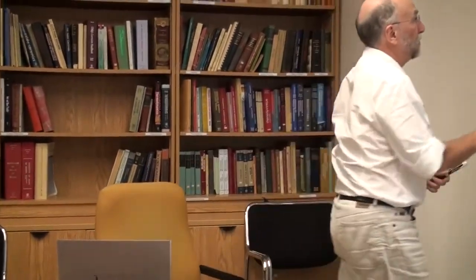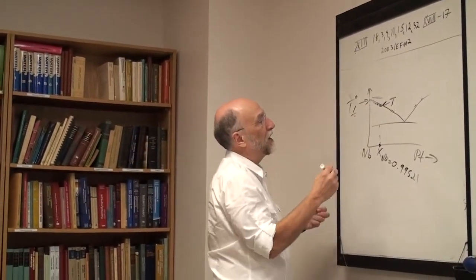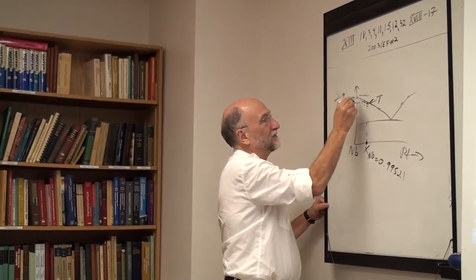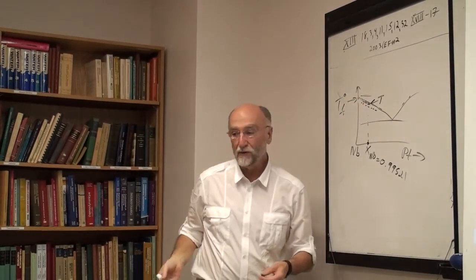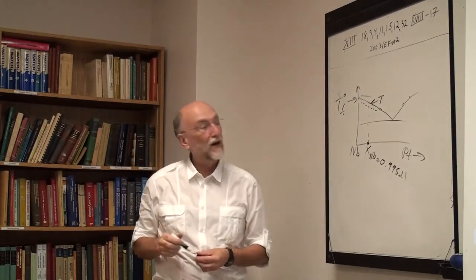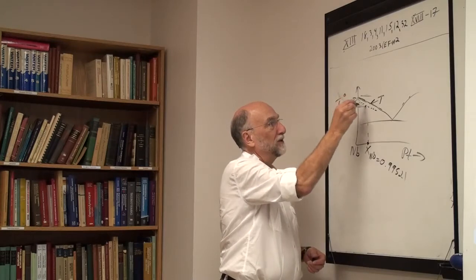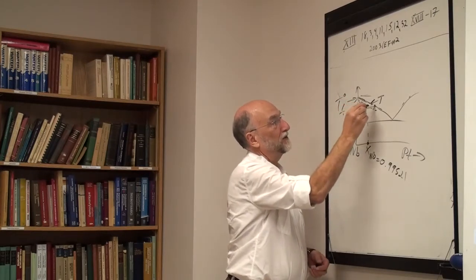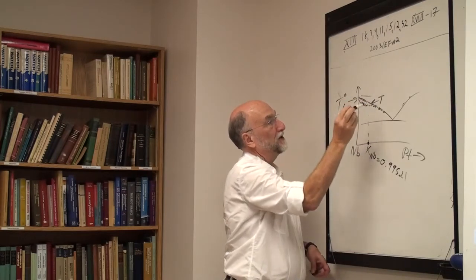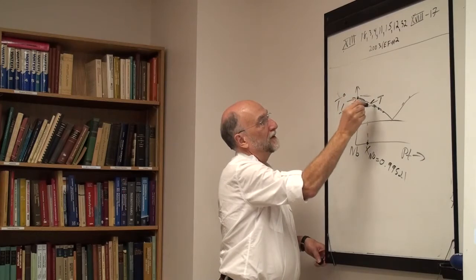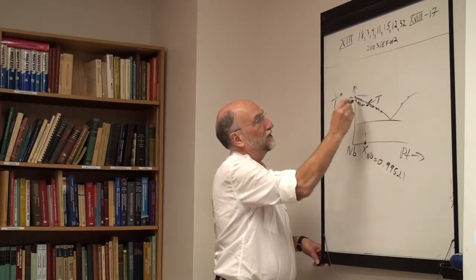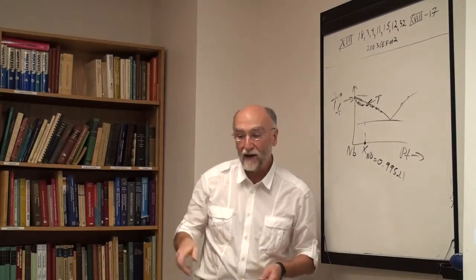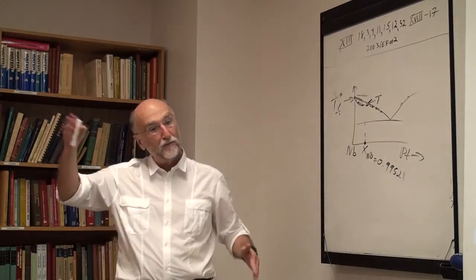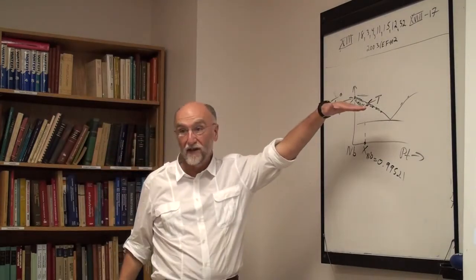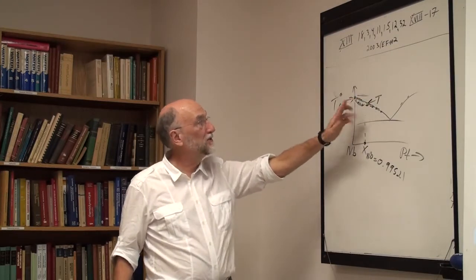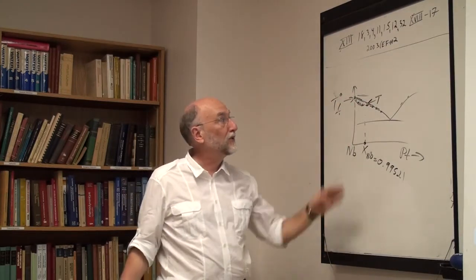Again, you see it's kind of masked. Suppose that you had some measurements. Say you're trying to optimize this thing and the measured liquidus is here. These are some measured liquidus points. And you're fooling around with your optimization and you're trying to bring in your G excess terms and your power series, and you find that no matter what you do, you're really having trouble getting these points down here. I've seen this in papers. These are the measured liquidus points, and you're trying to fit this, but you just can't fit these points here. Why can't I fit those points? You add a whole bunch of extra G excess terms, you put in cubic and quadratic terms, and you still can't fix the thing. The reason is that in this limit, as you approach niobium, the G excess terms become less and less important, have less and less effect.